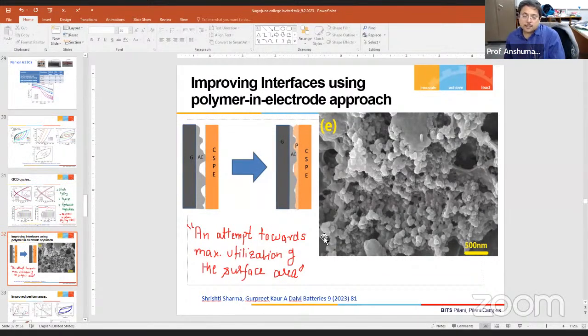What is the reason for this? The reason is that, as I have shown schematically in this picture, the activated carbon is unable to be utilized very properly when you have a solid-solid interface. Why? Because the polymer reaches only wherever it is able to go. But there are many holes and pores where solid electrolyte cannot reach the way liquid used to reach. So you have to find a way that the effective area of the activated carbon can be utilized without using the liquid. Now here the buffer layer should not have liquid.